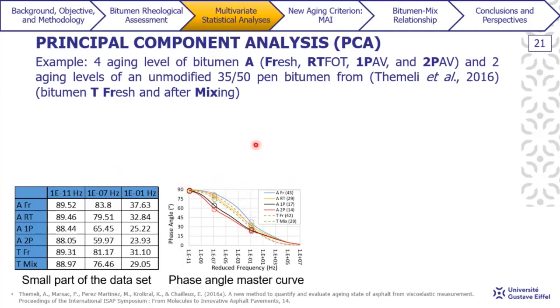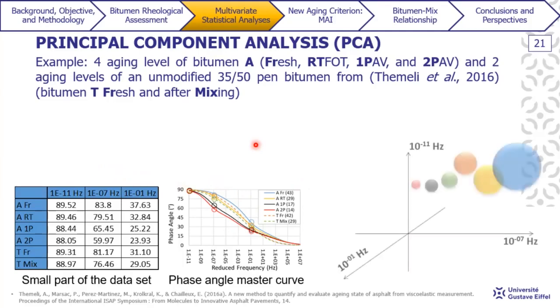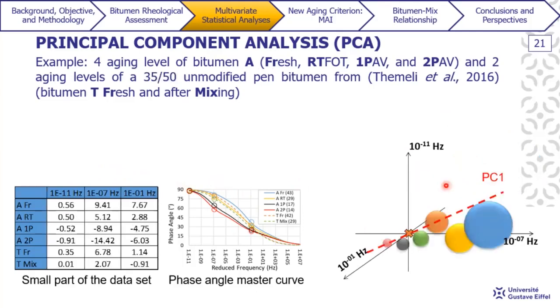So since we have 3 columns, we could represent this data set in a 3D graph. And if you had more than 3 columns, it would be impossible to represent it graphically. So here is our graph. The first step of PCA is data preprocessing, such as mean centering. We determine the mean value here, and then we subtract the mean value from each column to reduce potential bias terms. So in this case, we mean center our data set here at the origin of this 3D graph.